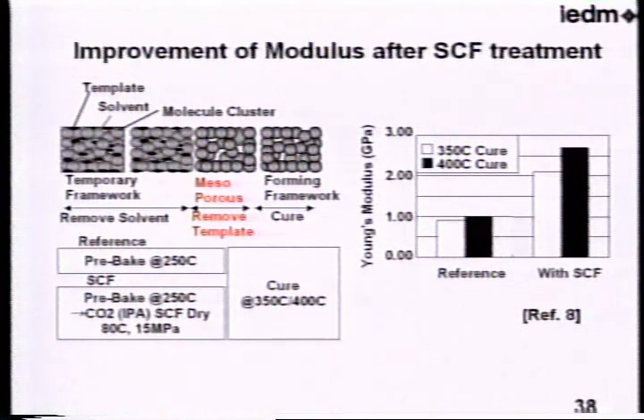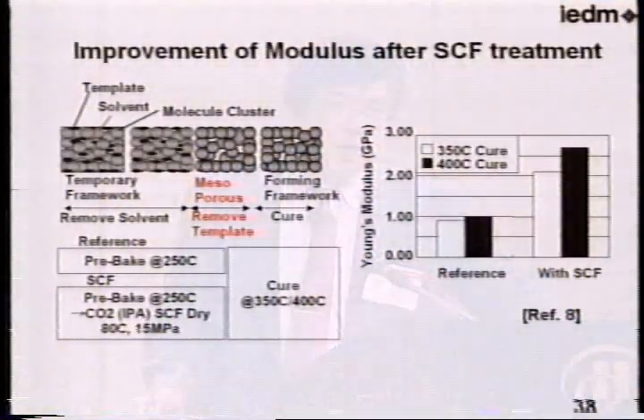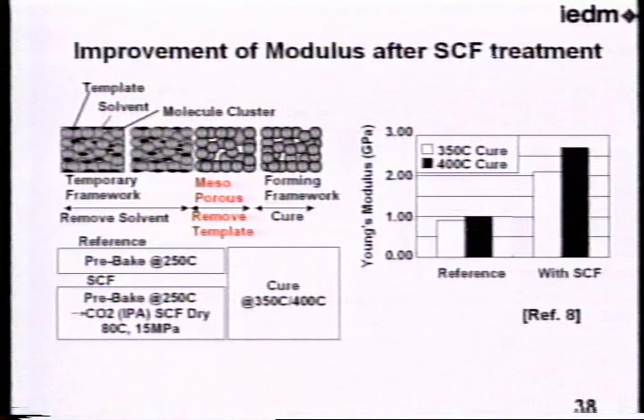We adapted CO2 supercritical fluid cleaning to a porous low K. We adapted supercritical fluid cleaning after pre-baking at 250 degrees C. And post annealing was followed at 350 degrees C. As you can see, the Young Modulus was almost twice after supercritical fluid cleaning, and this is because the supercritical fluid cleaning can chemically remove the template in the low-K film, and that will cause a smaller pore size.